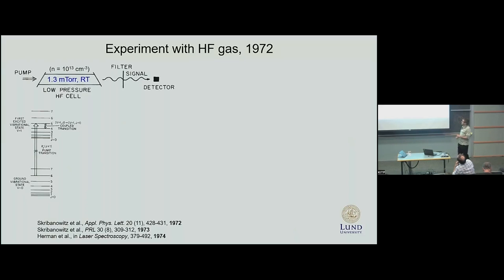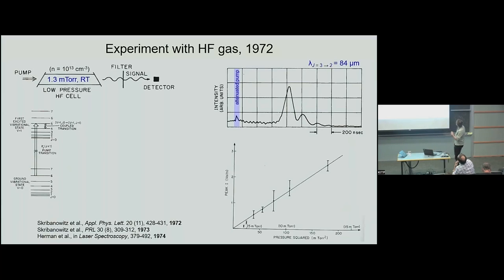The reason for that is you want to avoid any collisional quenching of the excitation, as a source of decoherence. This was observed on an infrared transition. Even though there are few particles per cubic micron of space, because the emission wavelength is so long, it effectively includes many, many molecules.